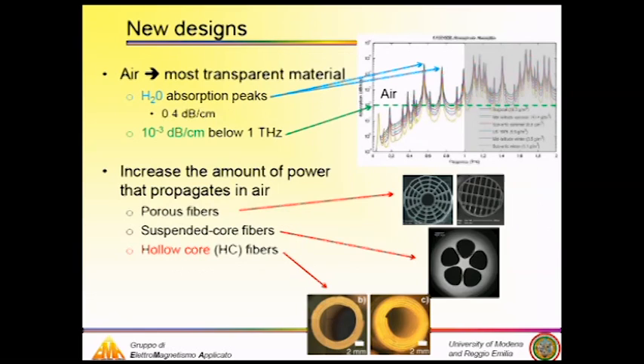Well, air is one of the most transparent materials. Here you can see a typical absorption spectrum measured with different kinds of atmospheres. You can see that below 1 Terahertz, the absorption is below 10 to the minus 3 dB per centimeter, even though there are some peaks due to water vapor, which is present in the air atmosphere. However, this very low absorption suggests a new way of designing optical waveguides, starting from, for example, porous fibers, microstructure suspended core fibers, and then finally hollow core fibers, which are what we are going to talk about today.